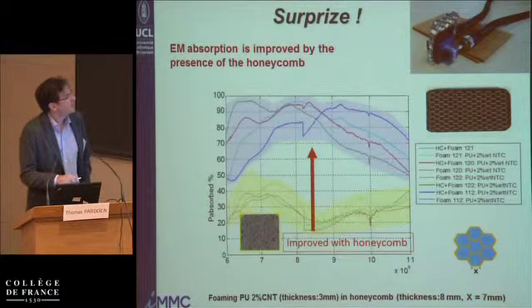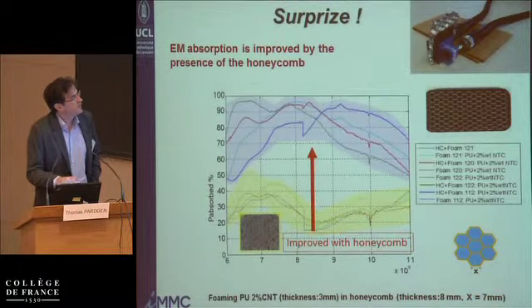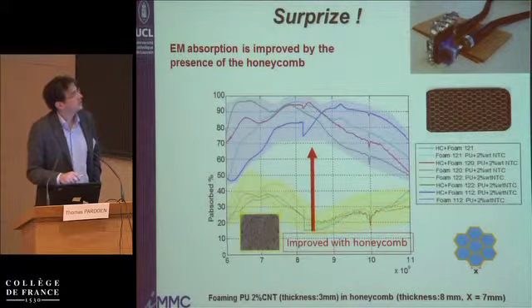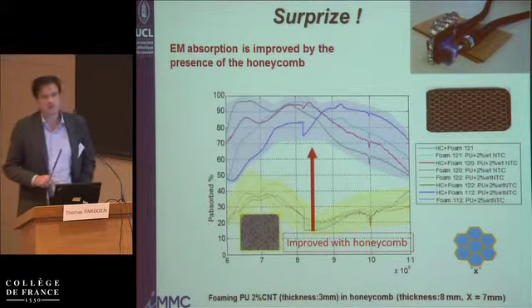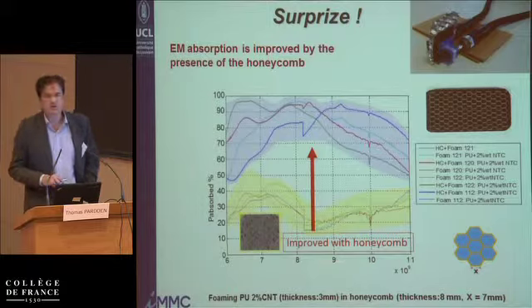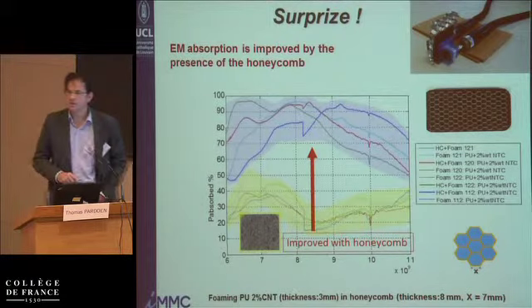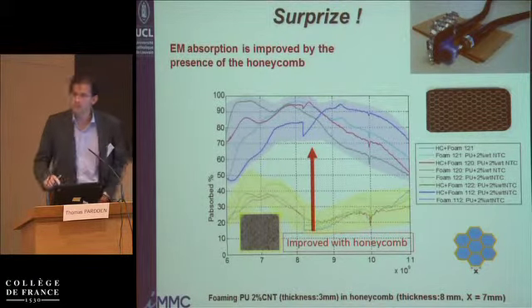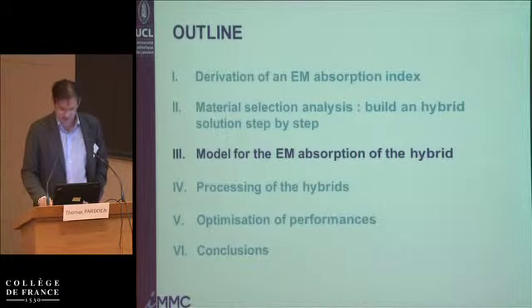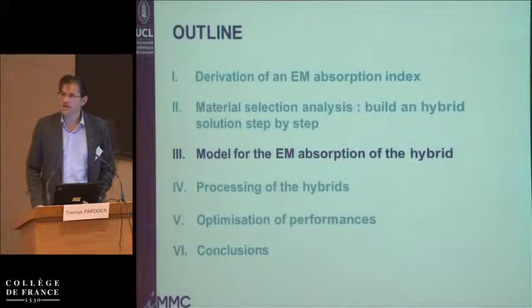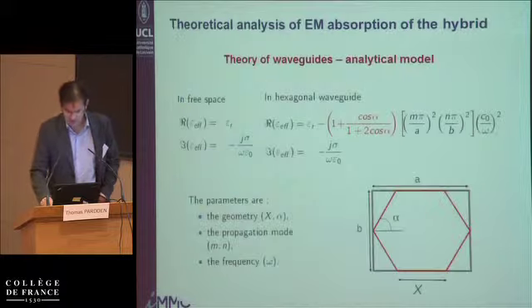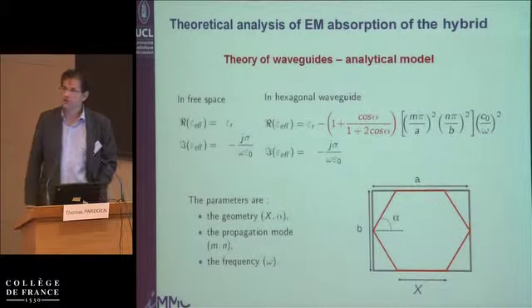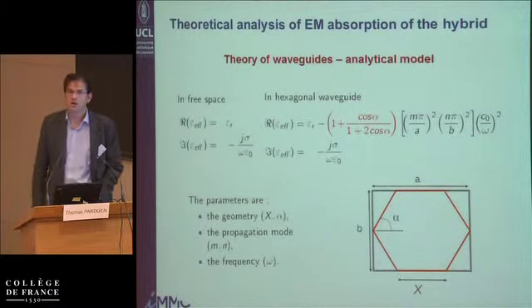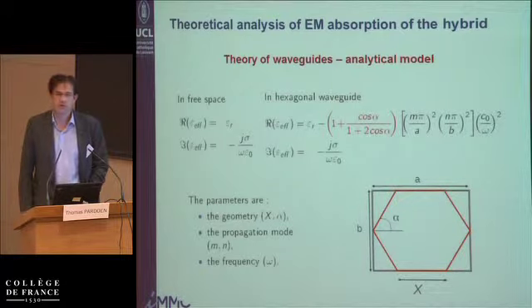So this was the absorption just of the foam with the nanotubes, and this was the result of the absorption as a function of the frequency for the foam inside the aluminum honeycomb. So very good news, because we got a synergy effect. And my colleague Isabelle Leinen and myself, we worked on trying to set up a model to explain why we are getting this improved electromagnetic